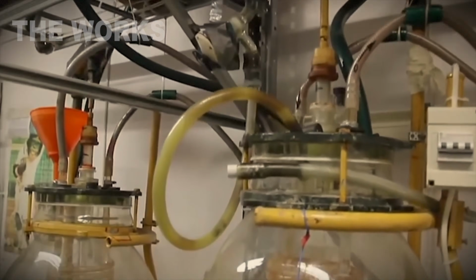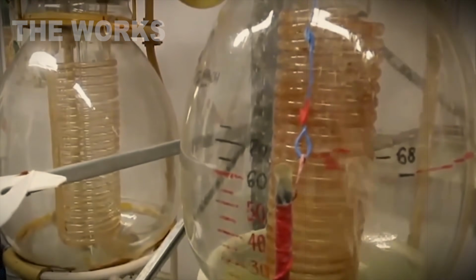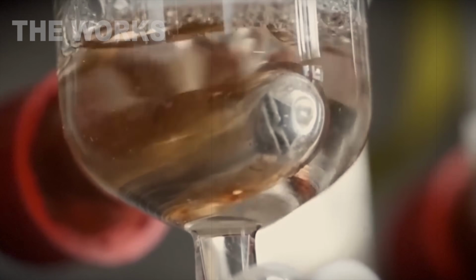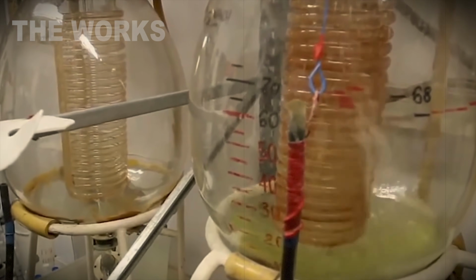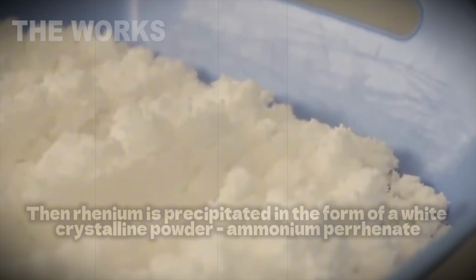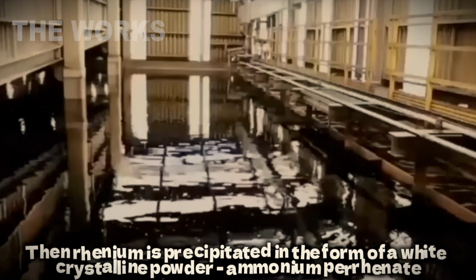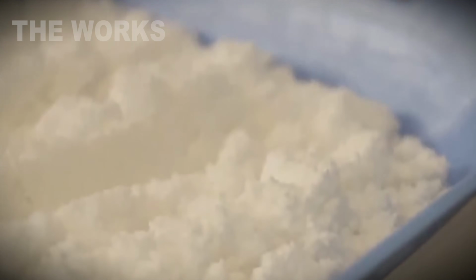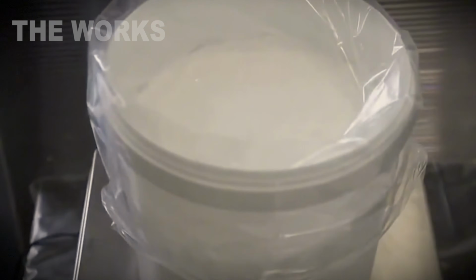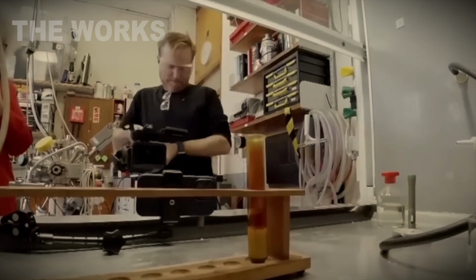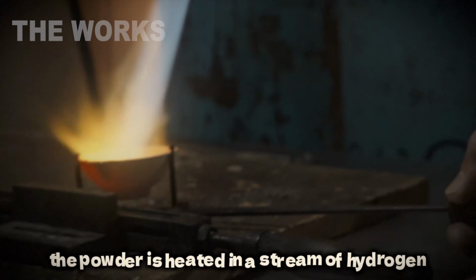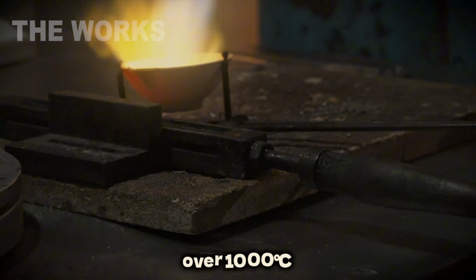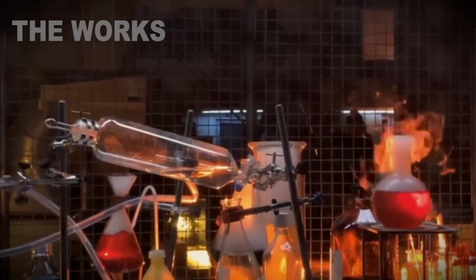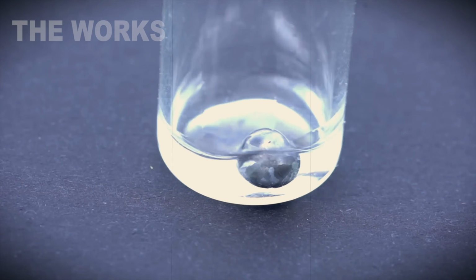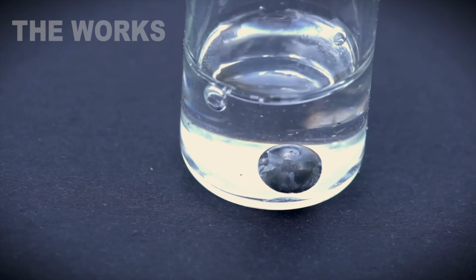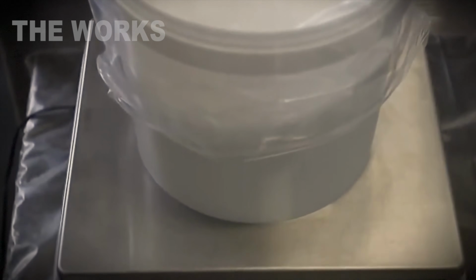The solution is purified of molybdenum, copper, lead, and other metal impurities through multi-stage chemical treatment: extraction, ion exchange, precipitation. Then rhenium is precipitated as a white crystalline powder, ammonium perrhenate. This is the most common form of rhenium feedstock for further processing. To obtain metallic rhenium, the powder is heated in a stream of hydrogen at temperatures exceeding 1,800 degrees Fahrenheit. Hydrogen reduces the rhenium oxide to pure metal. The result is rhenium powder, which can then be sintered, melted, or used directly in alloy production.